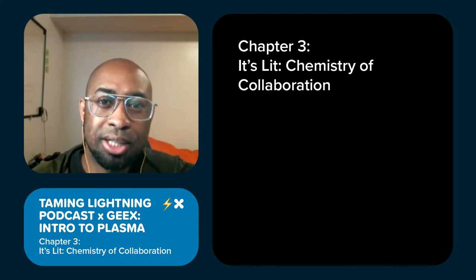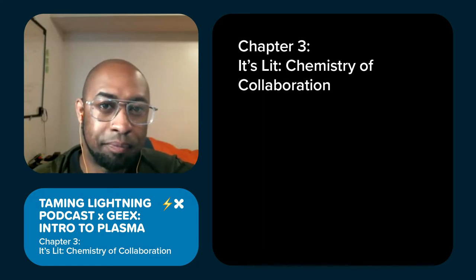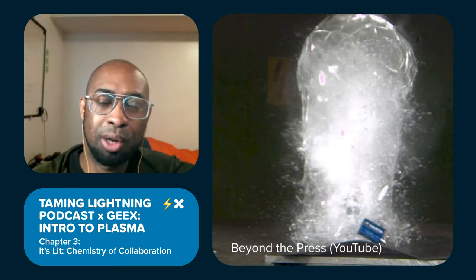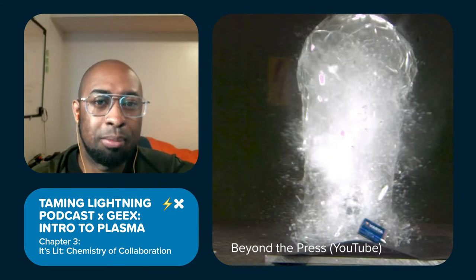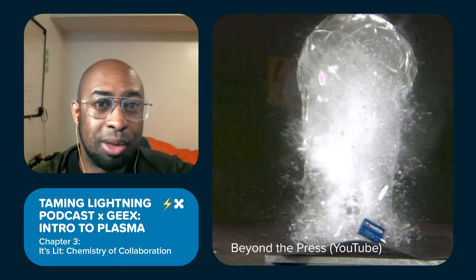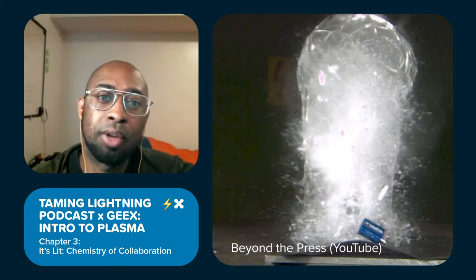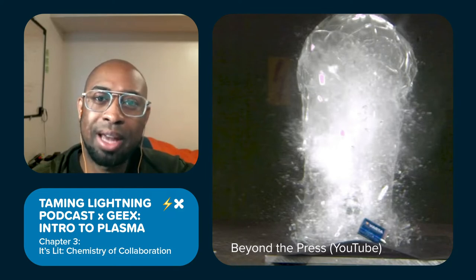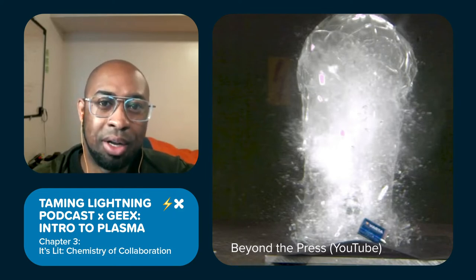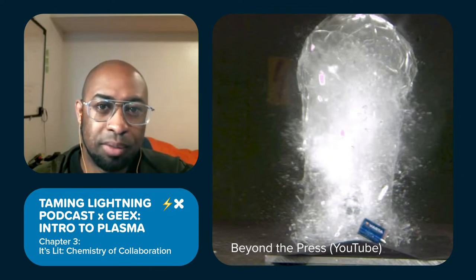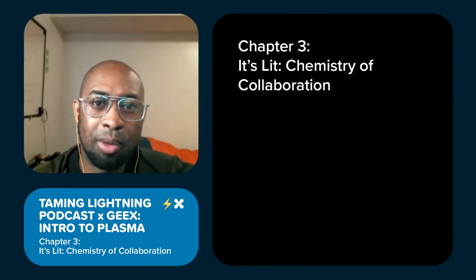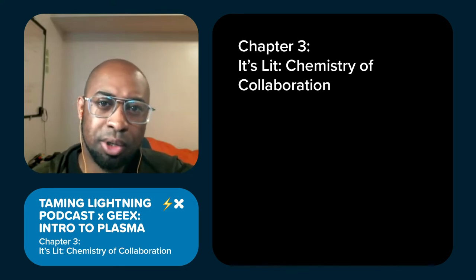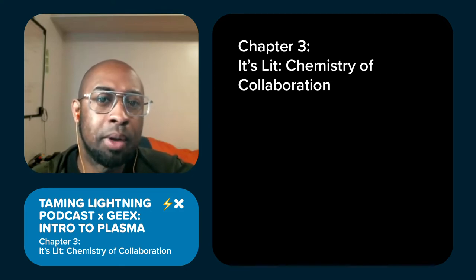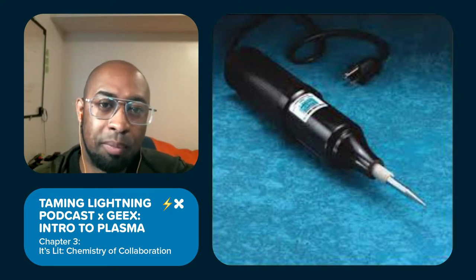Now, once the vessel is securely attached to the manifold, we can begin leak checking. Firstly, make sure you have an implosion barrier. If you're making a piece with a significant or potentially structural weakness, you definitely want to have this in place, as the first vacuum applied to the vessel is the moment that implosion can happen. Now, to create the physical barrier, use something like a plastic shield or heavy towel if you have any structural concerns. Then, pull the vessel under vacuum, which will go below 1 torr. Check with a spark or Tesla coil.